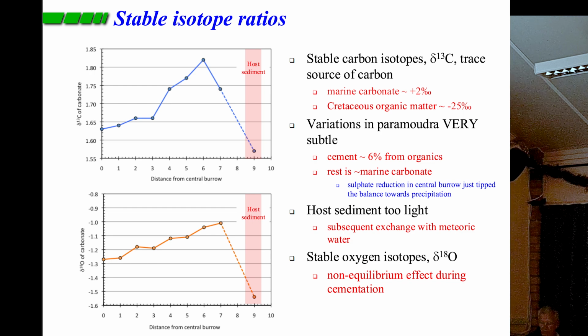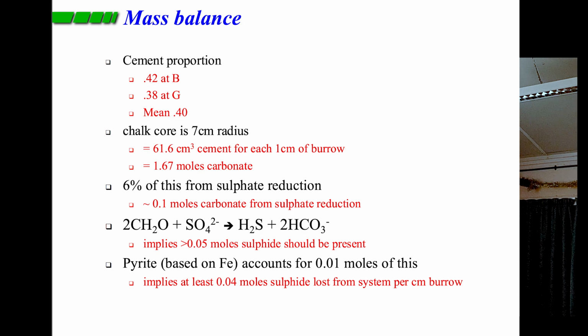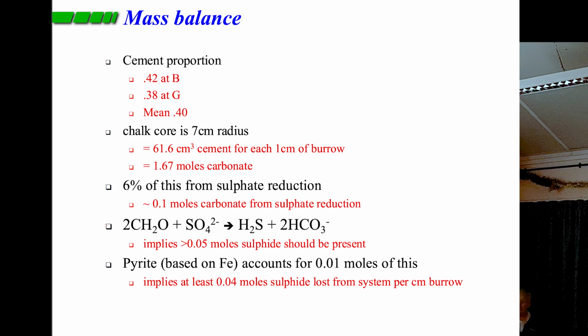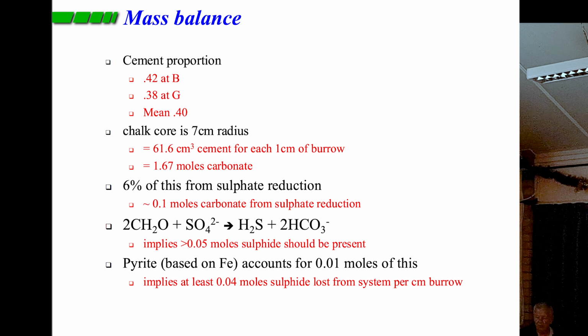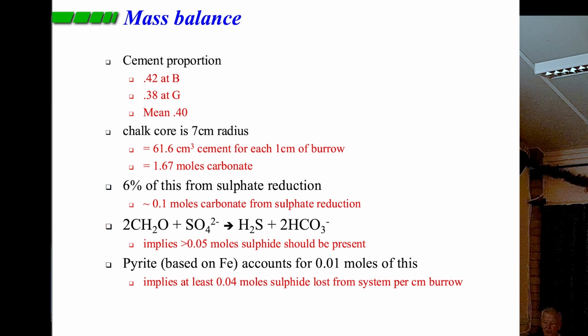There's also some problem in the host sediment out here, which is isotopically very light. I won't go into that. But what we can do now is some sums, calculations. Cement proportion, I showed you before, varies from about 42% close to the burrow down to about 38%. That's an average of about 40%.